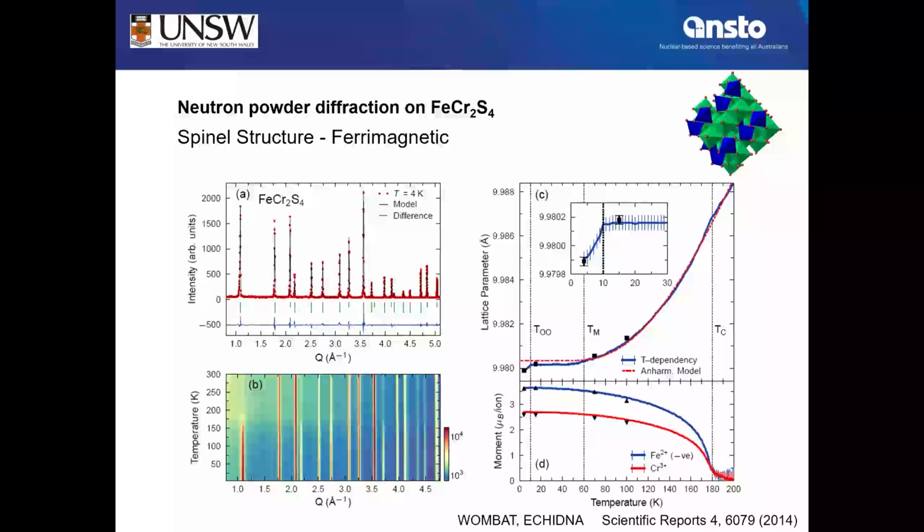So what do we learn from these two experiments? The core result is shown here. We determined the precise crystallographic structure and even more, the temperature dependence of the atomic positions. Here is shown the lattice parameter as function of temperature. There's actually a second orbital order transition, which we also nicely see. So high quality, super precise data.